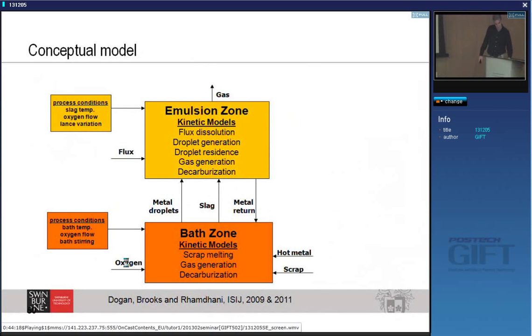All right, so at my university, we have developed this model of oxygen steelmaking. And we have split the reactor into two zones. One zone where the jet hits the bath and there are reactions. You make droplets, the droplets go into the emulsion and then they return. You make slag here and the slag goes there. Along the way, we've had to develop models about the flux, the droplets, the gas, the decarburization, the scrap melting, the decarburization in the bath zone.